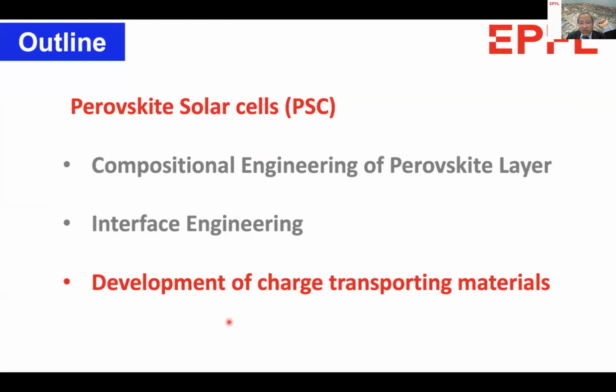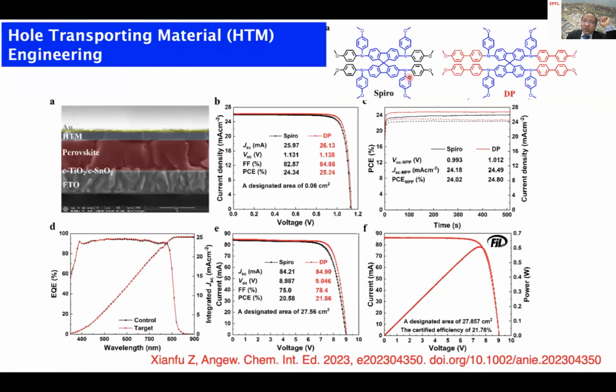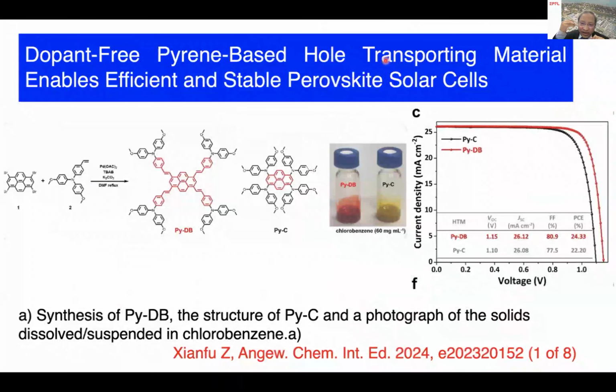I quickly turn towards the charge transport medium. I'm just giving you a few examples so that people can think of their own new materials. So here is the typical charge transport material, spiro-OMeTAD, well known in the literature. What we have found is that spiro-OMeTAD is not very stable because it has to be doped, because conductivity is low. The dopant induces the instability. So what we thought is, can we migrate the positive charge over a larger distance? So we increased the pi conjugation, and then we made this molecule with the dopant, and we reached similar efficiencies like spiro. It's fine, but still it's a dopant. Now, can we do it without doping?